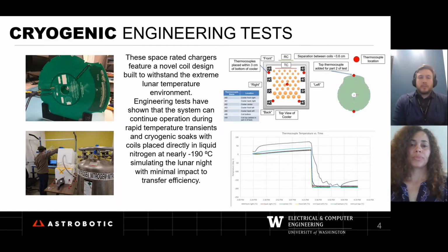Some of the initial tests that have been performed so far are subjecting the transmitter coils to liquid nitrogen temperatures. We have essentially put these into a liquid nitrogen chamber and allowed them to climb up in temperature to at peak about plus 70 degrees. And then in the most extreme transient, we brought them down to liquid nitrogen temperatures by dousing them in pure liquid nitrogen down to negative 190 C.